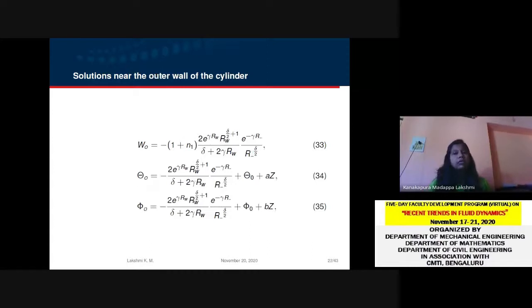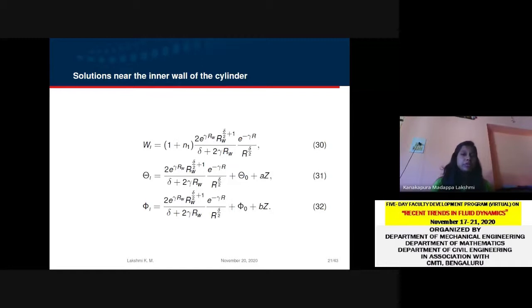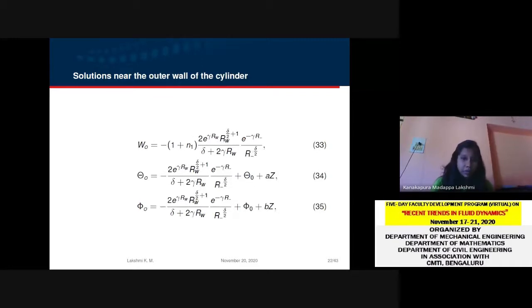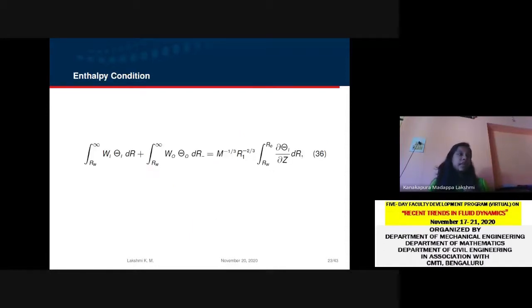Equations 30 to 32, and then solutions at the outer wall of this cylinder are given in equations 33 to 35. In the solutions 30 to 35, we can observe that all the solutions are known, but A and B are still unknown. A and B appear in equations 34 and 35, which represent the temperature and concentration gradients. In order to find the equations for these temperature and concentration gradients, we have used the enthalpy condition.